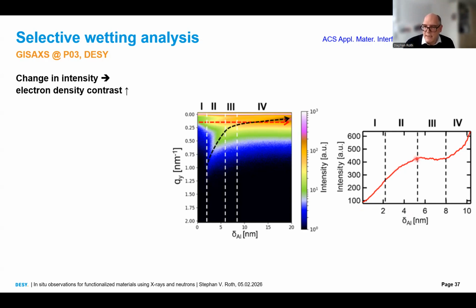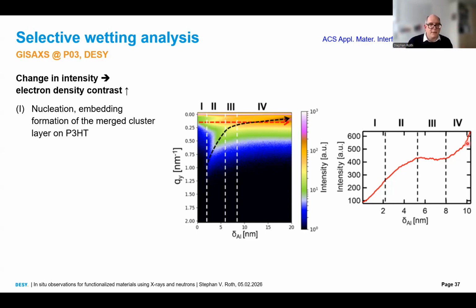And then suddenly this intensity starts to decrease, because then I fill up the other part, the PMMA. The PMMA is saturated, and I grow on the PMMA, and hence the scattering contrast goes down, and then we have an overall increase in the signal because we have aluminum growing on top and the X-ray scatter on the aluminum. And this is what we then can find out.